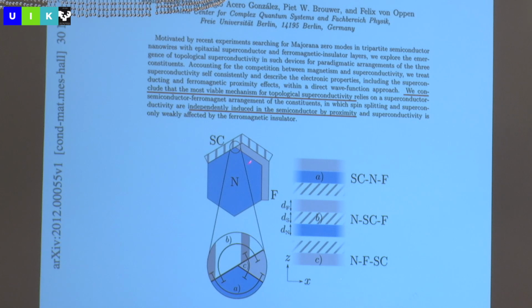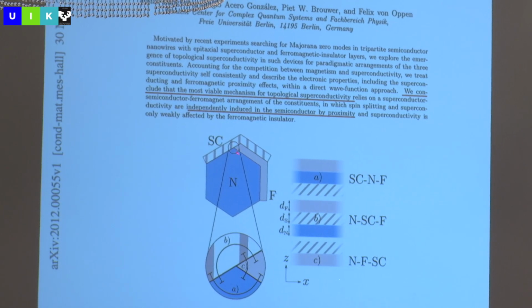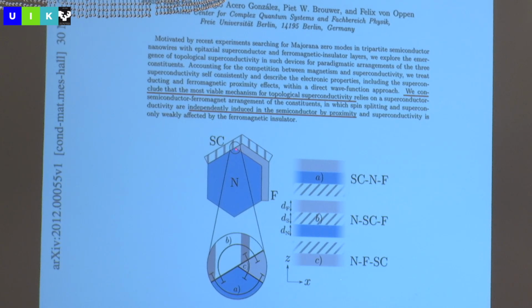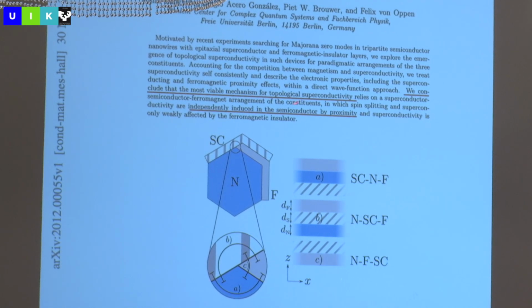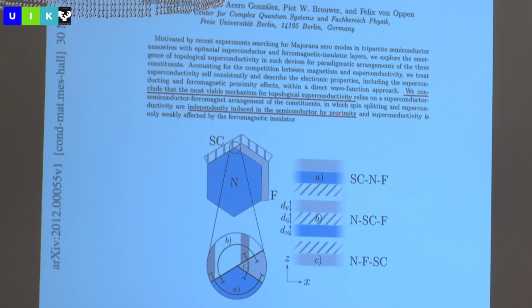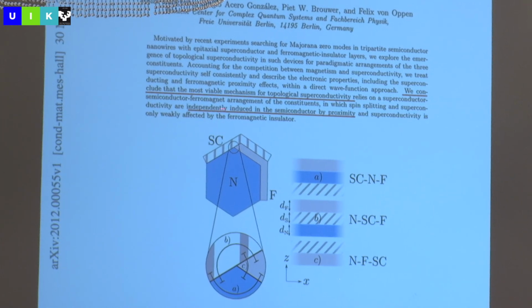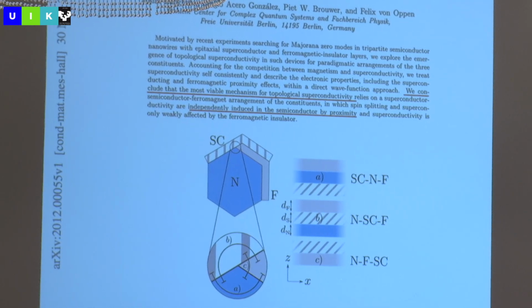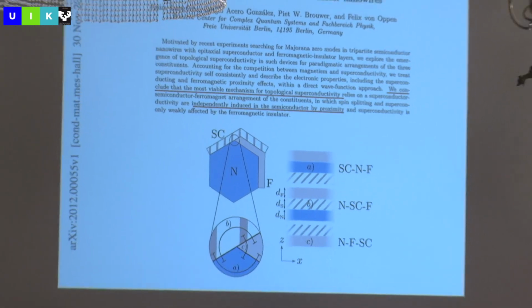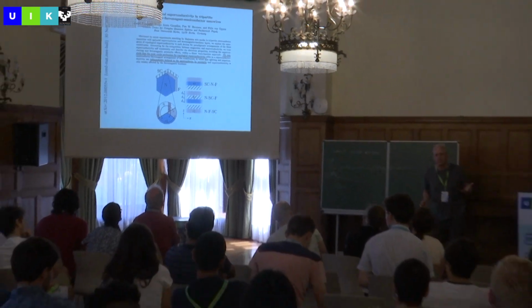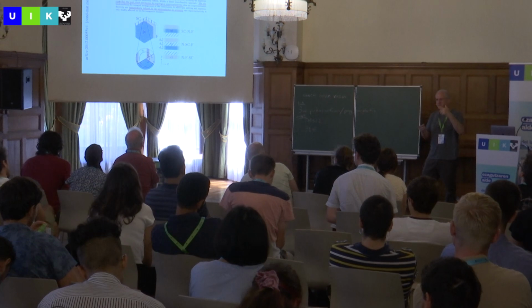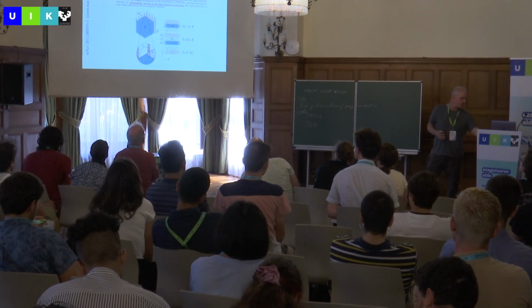Berlin. And here they find that, in fact, it was like in the Moodera experiment, that it was sitting at the interface between the superconductor and the ferromagnet that made the most difference. And at that interface, what they say is, we conclude that the most viable mechanism for topological superconductivity relies on a superconductor-semiconductor-ferromagnetic arrangement of its constituents in which the spin splitting and superconductivity are independently induced in the semiconductor by proximity. So it needed some direct induction as well as the induction in the superconductor. And now we have a much richer understanding of where in the phase diagram this triple component system will have superconductivity.